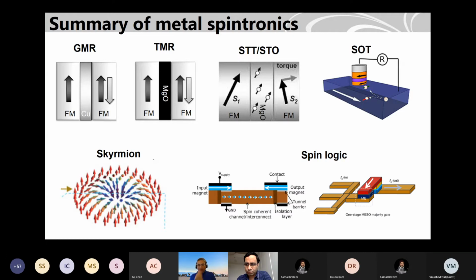Then another question from Manipal Singh: is the momentum relaxation time related to the spin relaxation time? Can we get this spin diffusion length longer if we make our conductor more ballistic? Okay, so yeah, you have to consider two separate quantities for momentum relaxation and spin relaxation. Of course, they are related, but momentum relaxation time can be in femtoseconds or picoseconds. But spin relaxation time can be nanoseconds and microseconds. So, for example, spins can scatter many times in, for example, aluminum or graphene with low spin orbit material, but spin orientation can still survive.